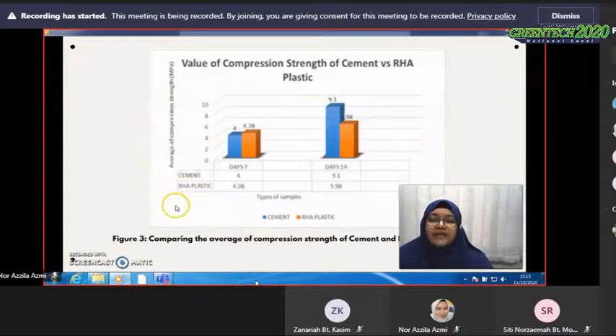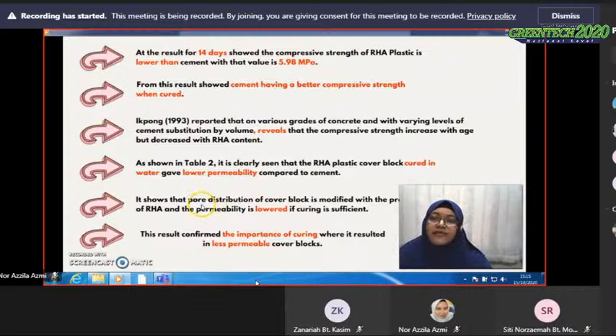Figure 3 shows the comparison of the average compression strength of cement and RHA plastic. At 14 days, the result showed the compressive strength of RHA plastic is lower than cement, with a value of 5.98 MPa. This result shows cement having a better compressive strength when cured.